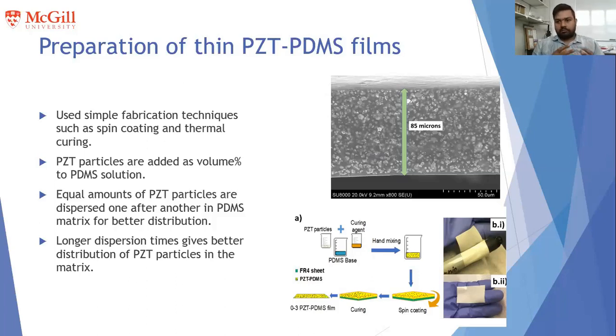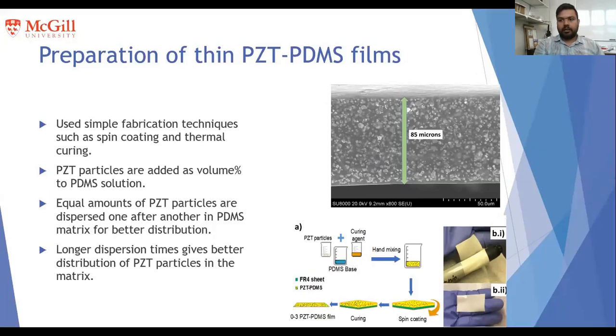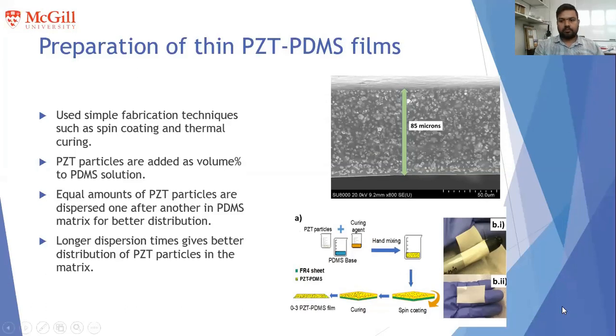We prepared these films in different volume percentages, though we report only one volume percentage's results in this article. Volume percentage means the proportion between PZT nanoparticles and the total PDMS solution. Here you can see the cross-section SEM image of the film as well. The white dots all over the film are the PZT particles.